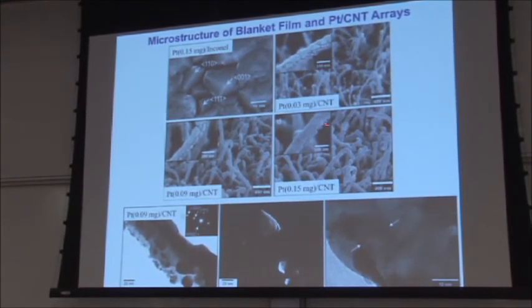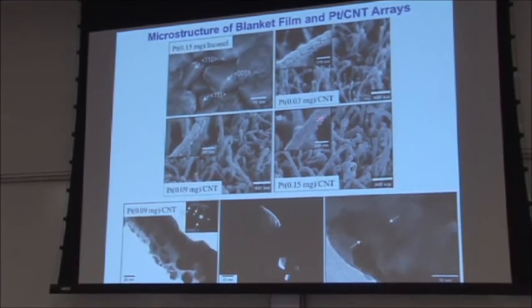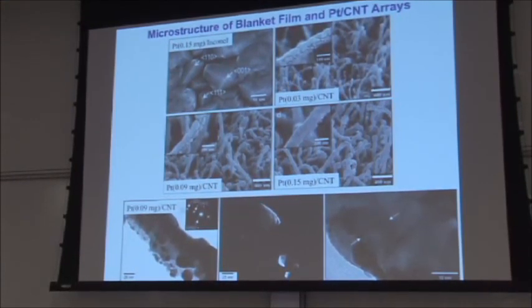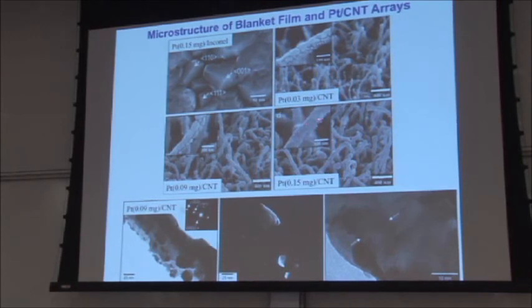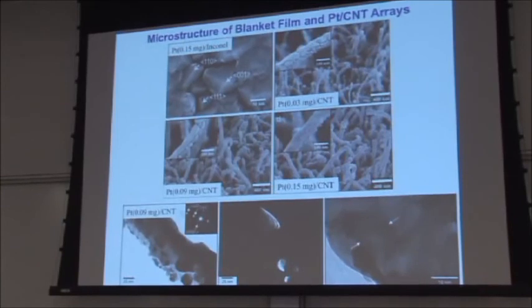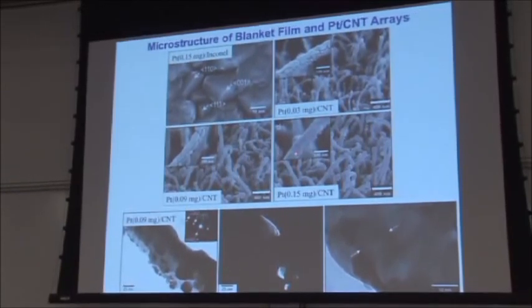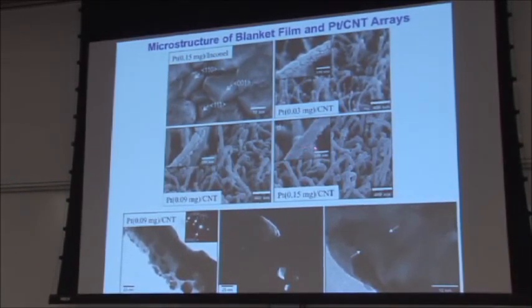And you would expect this because there's really no intermediate phases between platinum and carbon. There's negligible solubility at elevated temperatures and, of course, at room temperature. And really, platinum is reported to bond to defective and functional groups on the carbons, but it's still not, well, you could tell it's just not very good bonding between the two. So you have this kind of platinum architecture with coarse and fine crystallites sitting on the CNTs. And actually, you can image the platinum crystallites, and you can actually image the carbon nanotubes through the platinum.